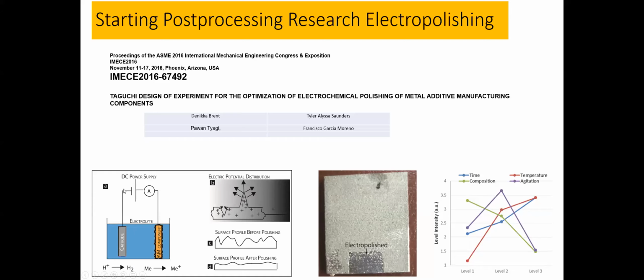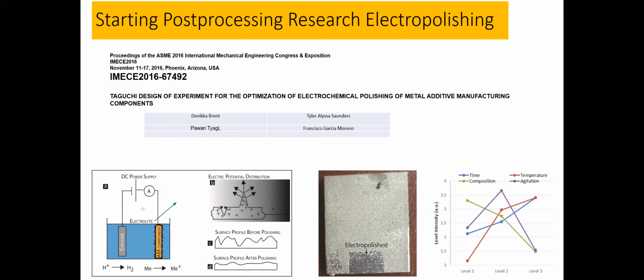Let me see if I can use annotate and my tool. Okay, yeah, so I'm here. This bath is made up of an acid solution, almost 70% phosphoric acid and 30% sulfuric acid. We put in a cathode, which is generally tantalum coated stainless steel, and then our AM component is submerged, and then we apply voltage or we control the current.